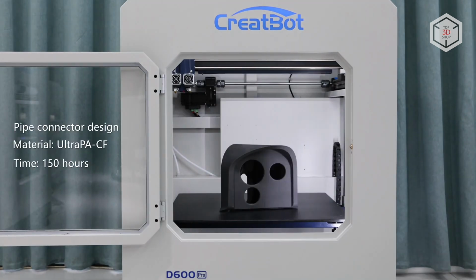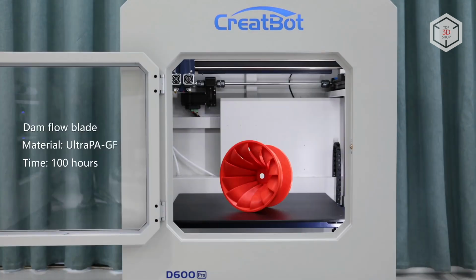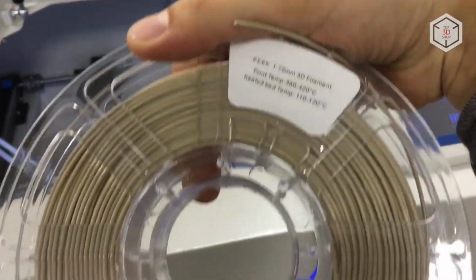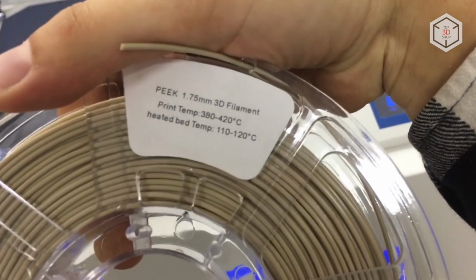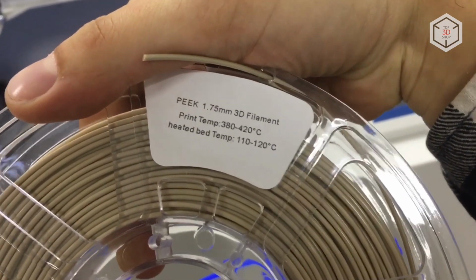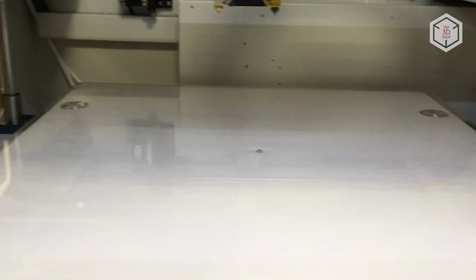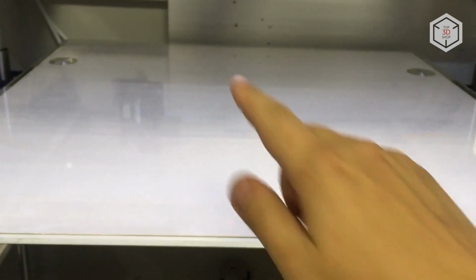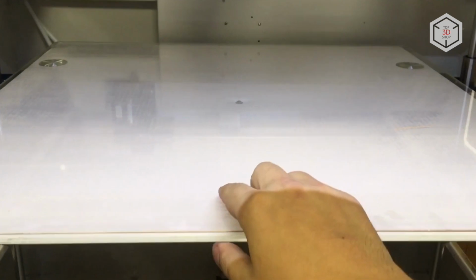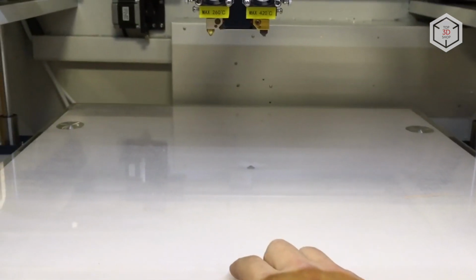Although the manufacturer does not claim that this printer is capable of working with high-temp filaments, in this review we will try to print a small gear with PEEK at a temperature of 410 degrees Celsius. The machine has a closed chamber and is equipped with a powerful heating system. We're going to print on a glass surface with the chamber heated up to 60 degrees. We will also apply a layer of glue that was included in the kit to improve the adhesion of the printed model to the platform. Let's turn the printer on.